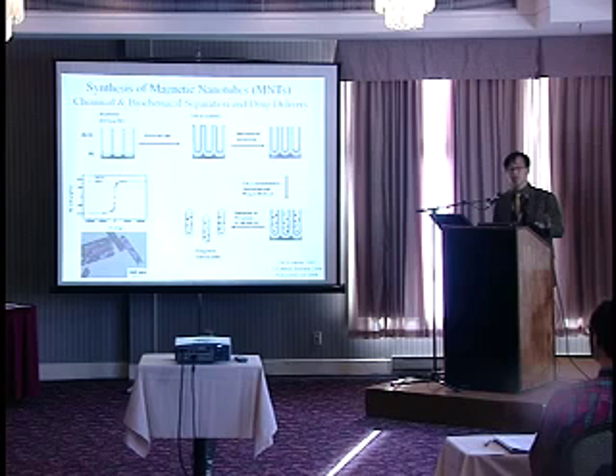These days, we are really focusing on magnetic nanotubes, and we made this magnetic nanotube by simply putting magnetic particles in this silica nanotube. So this is a simple process for the synthesis of a magnetic nanotube. You have a porous template and silica coating, and then before you release the nanotube, you put in these magnetic single crystals. Actually, not putting them in, you synthesize these magnetic single crystals directly in the nanotube, and then release them out. And now you have a magnetic nanotube, with magnetic properties.